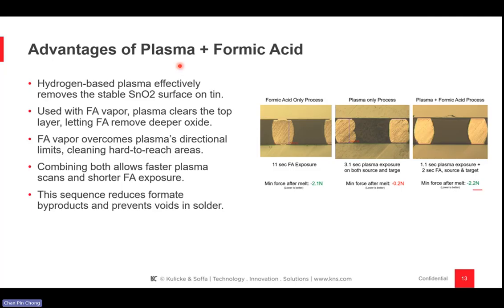And when we introduce the hydrogen-based plasma, it effectively removes some of the tin oxide on the tin surface. With the addition of both formic acid vapor and plasma, it clears the top layer, letting the formic acid remove a deeper oxide. Formic acid vapor overcomes some of the plasma directional limits for cleaning hard to reach areas. So that's why we believe that the two could be complementary. So combining both, plasma scans and shorter formic acid exposure gives you a very nice clean bond. And this sequence also reduces the tin formic byproducts, and also prevents voids in the solder.